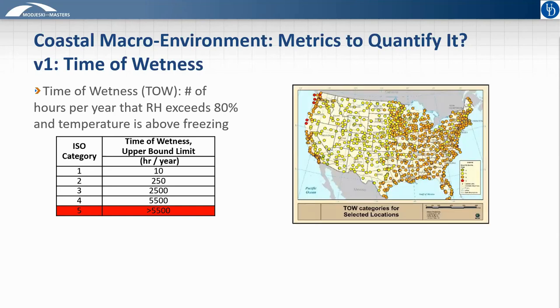Steve Chase compiled the data shown here on the right, which shows that Category 5 levels of time of wetness are relatively rare, being limited to areas along the Pacific Northwest coastline. Those are the only places we're seeing the red dots representing time of wetness 5. So our recommendations for this level of time of wetness were based on reviewing the performance of uncoated weathering steel bridges that existed in that time of wetness 5 environment.